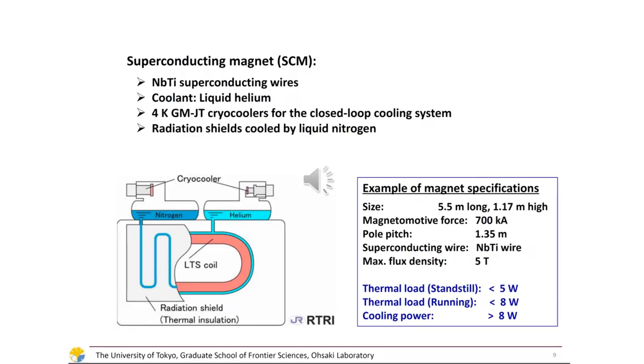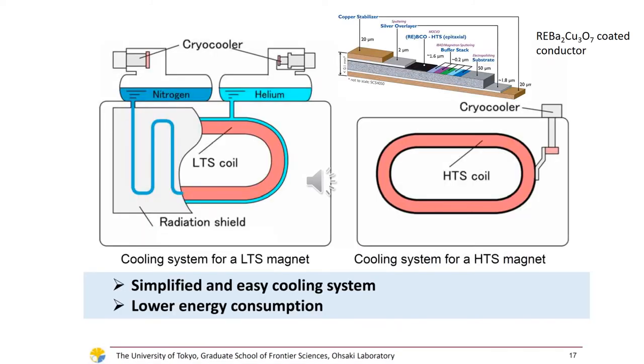Here we see the principle of the cooling system and some specifications of the coils. The work is in progress to replace the low-critical temperature niobium-titanium coils by coils with high-critical temperature coated conductors that can be cooled with liquid nitrogen.